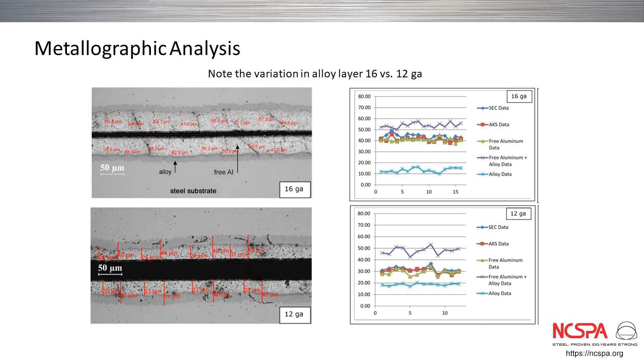Another important characteristic is that the alloy layer, which is a stoichiometric variable composition of iron aluminide, is a little less than twice the density of the free aluminum layer. Free aluminum layer is about 2.7 specific gravity. The specific gravity of the alloy is between 4 and 4.5. So the thicker that alloy layer, the more dense the net coating becomes. You have to channel your inner Archimedes.